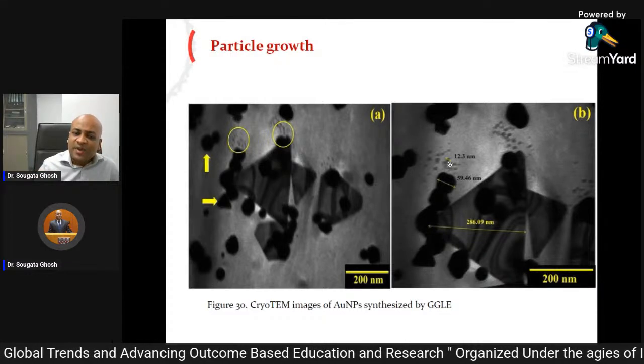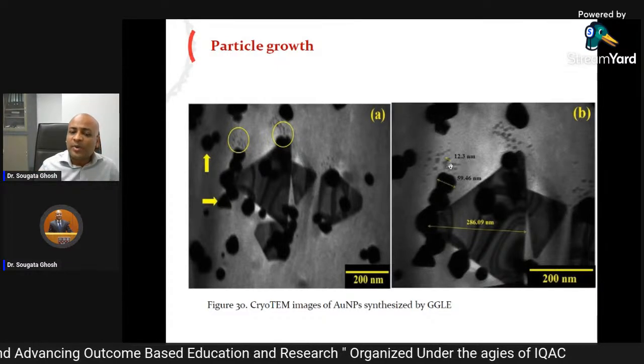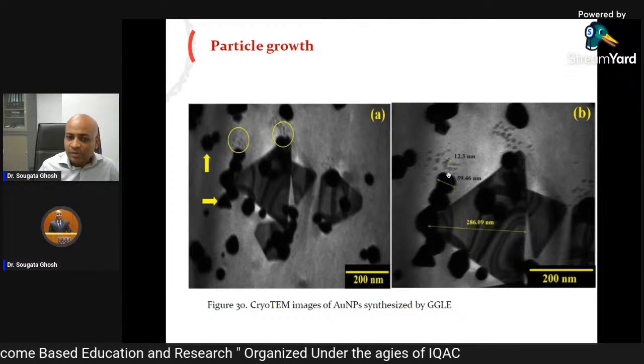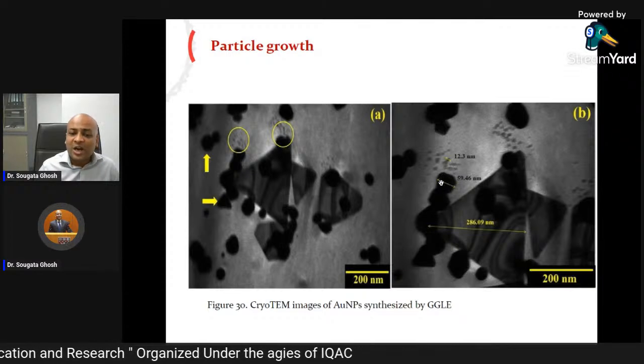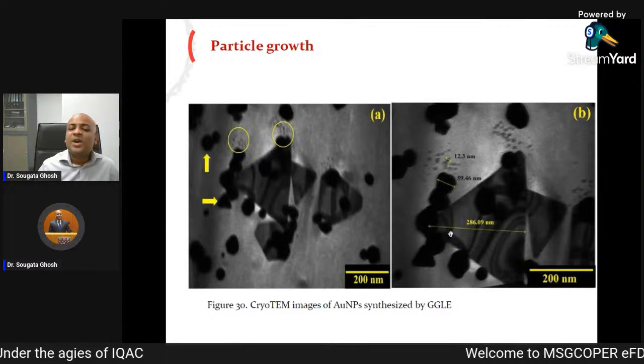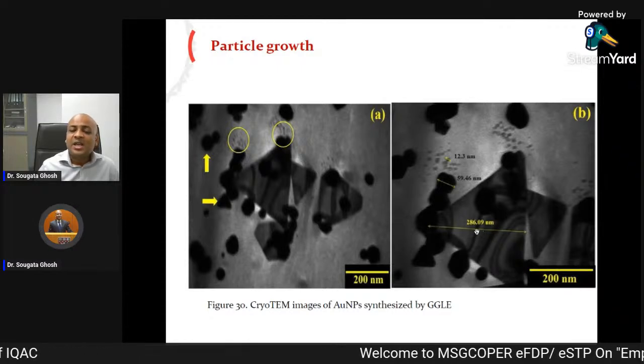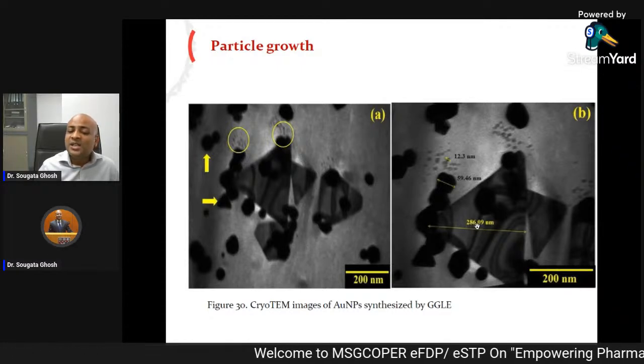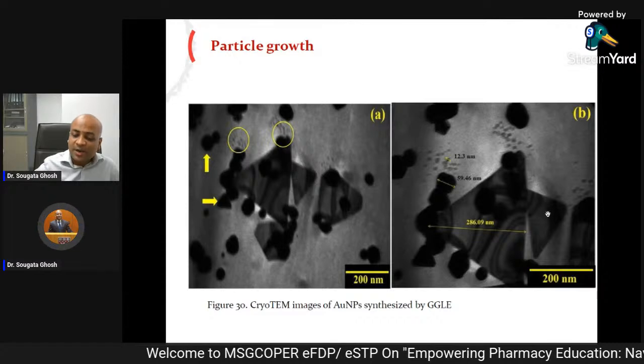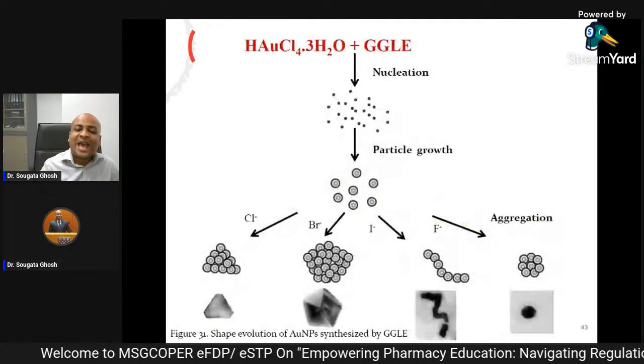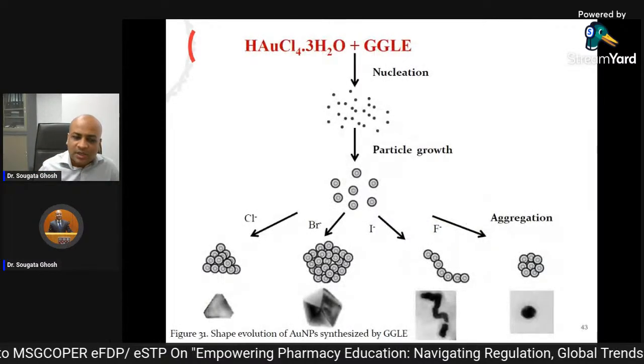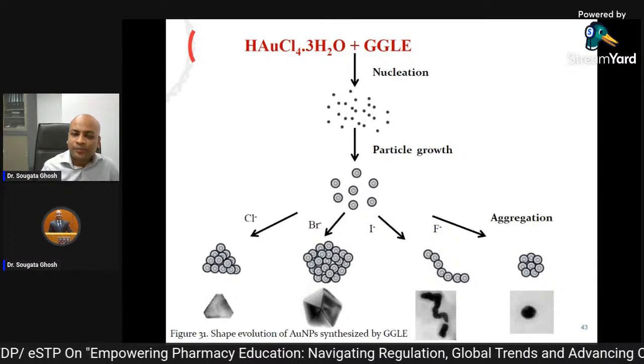Initially very small, 12.3 nanometer nanoparticles were formed. They were coming together to form bigger nanoparticles of 59.46 nanometer. They are coming together to form much bigger triangles around 286 nanometer. Ostwald ripening process. So we thought, can we modify the process over here? Can we control the shape?